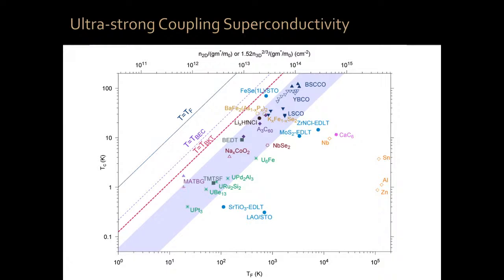Okay? Now, if you look at magic angle twisted bilayer graphene and magic angle twisted tri-layer graphene especially, these are among the strongest, if not the strongest, superconductors that we know. They have a minute density of electrons, just a few electrons, and they superconduct very strongly. They have relatively high Tc. If the high temperature cuprate superconductors had the same coupling strength as magic angle graphene, they would be well above room temperature superconductors. Okay? So one of the mysteries in the field is how come that magic angle graphene and the tri-layer graphene, with so few electrons, superconduct so strongly? What is the key physics, the key ingredient that allows that to happen? And can we recreate that key physics in other materials at higher densities? And higher densities will mean much higher critical temperatures, okay?